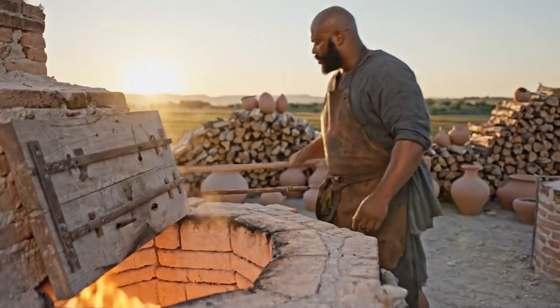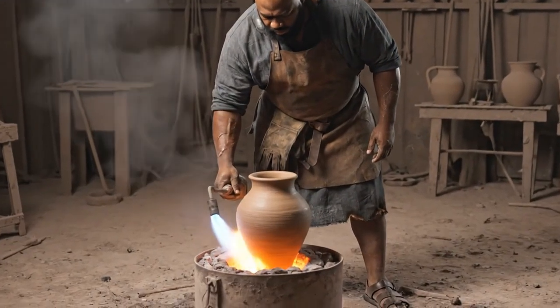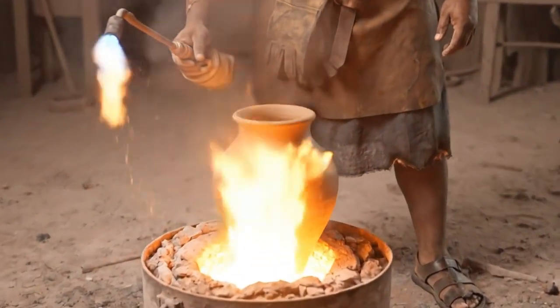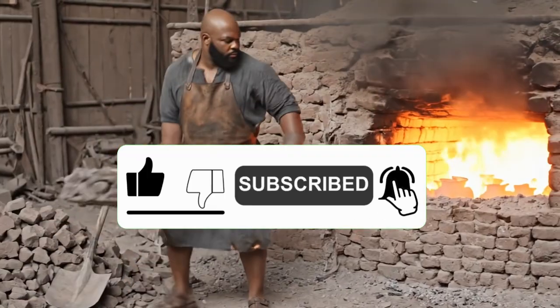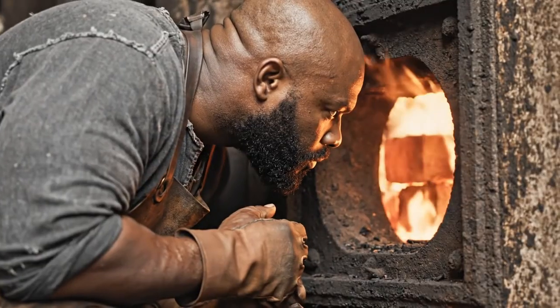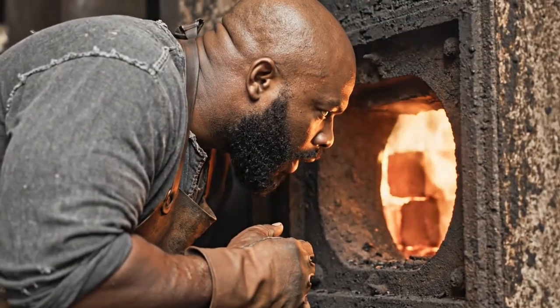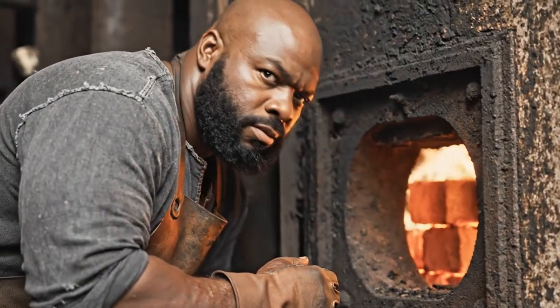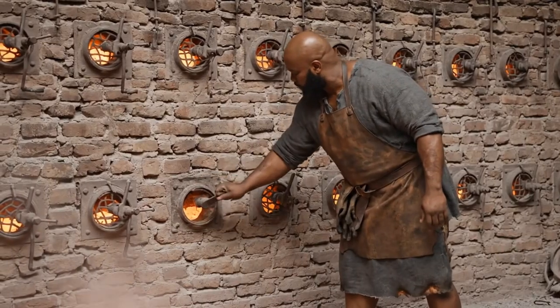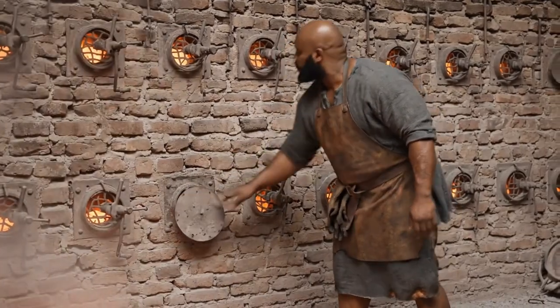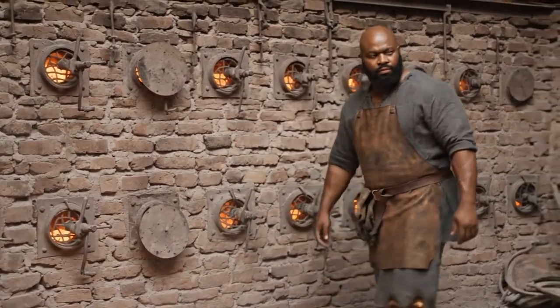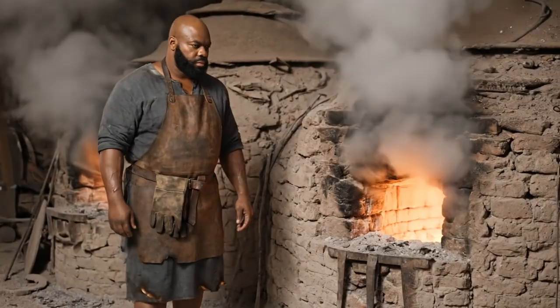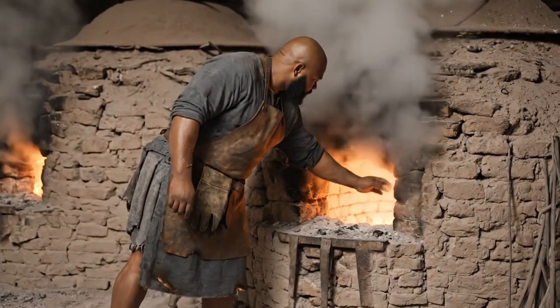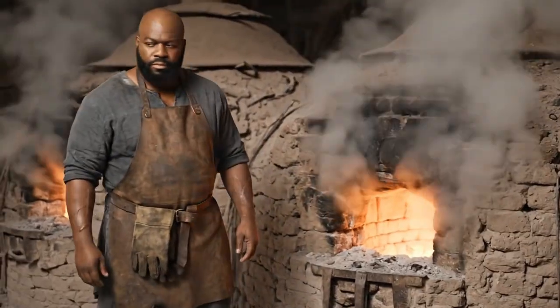The firing begins at dawn because the workers need daylight to monitor the process, and it's not a simple matter of lighting a fire and walking away. It's a continuous operation lasting 30 to 40 hours, where experienced firemen are constantly feeding fuel, monitoring temperature by eye because they don't have thermometers, but they can judge heat by the color of the flames and the glow of the bricks visible through small inspection ports, and making constant adjustments to airflow by opening and closing vents in the kiln structure. The temperature is rising gradually through distinct phases that the Babylonians recognized by experience.